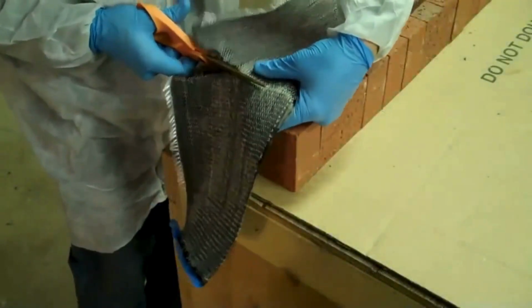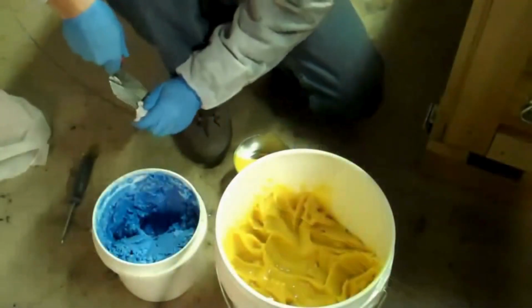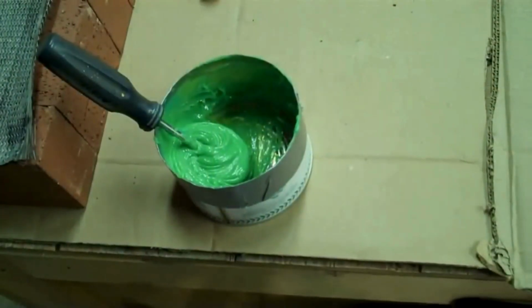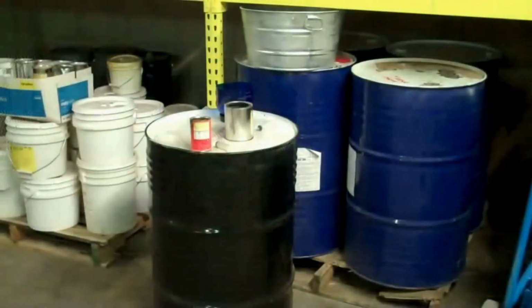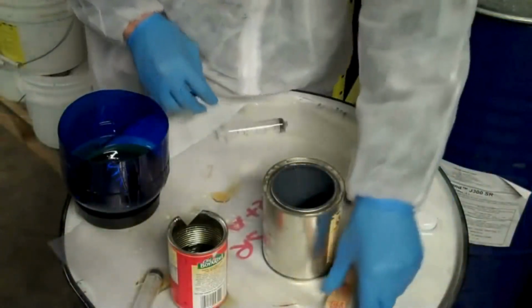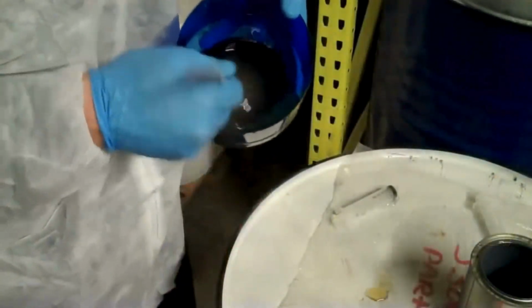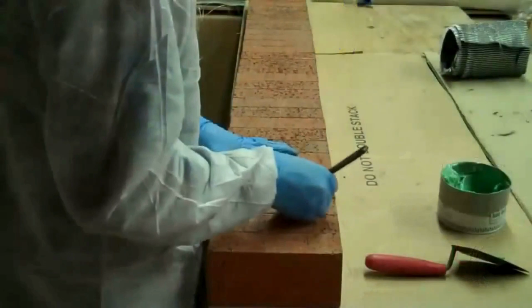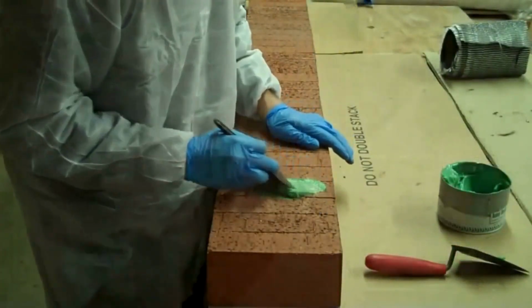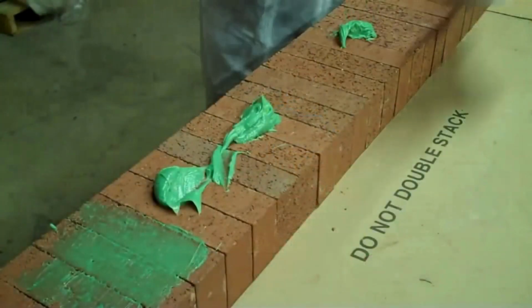As you see, we are cutting the length of the fabric to the length that we need. This first epoxy, which has a consistency like toothpaste, we call a tack coat. We put that first on the back of the bricks and spread it to get rid of any of the sharp edges. And here he's putting that on the back of the brick, spreading that, getting rid of any of the sharp edges there.